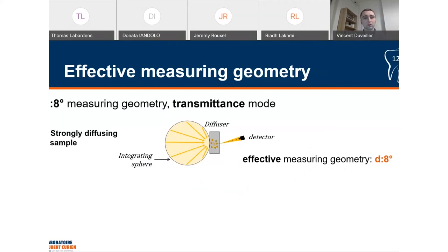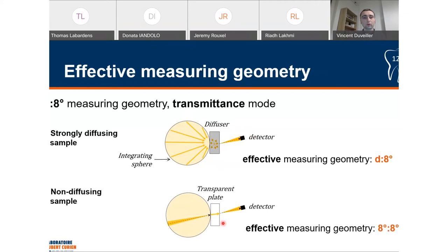Here you can see a drawing of our device of hemispherical directional geometry when it's used to measure a transmittance factor of a strongly diffusing sample in the first case. So for example, a white paper. As the sample is a strong diffuser, the detector collects the radiance from the whole integrating sphere. And therefore, the effective geometry is hemispherical directional. So it matches the geometry of the device in this case. In the second case, when it's used to measure the transmittance factor of a non-diffusing sample or a transparent plate, for example, the detector only sees the radiance from one direction, and therefore the effective measuring geometry is bidirectional. So it's different from the geometry of the device.